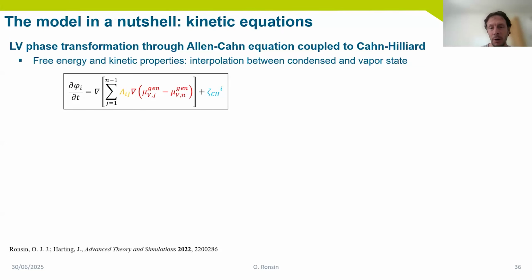On the left, you have the volume fraction of the solute. So the x-axis, this is the film height typically, and you see that you start here with a 10% solute. And with increasing time from blue to red, the film height decreases, of course, and the solute volume fraction increases up to 1. And on the right, you have the solvent volume fraction, which of course decreases over time. So this is how a single simulation looks like.